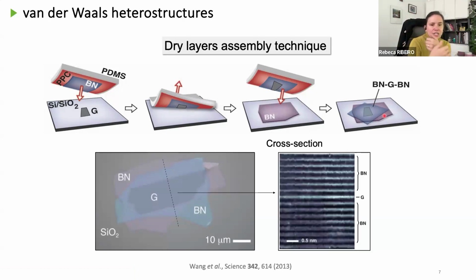And if we make a cross-section of this material, and we observe it by TEM, we can see that there is nothing between the layers. So there is nothing gluing the layers together. Here we are really talking about materials that are held to each other by van der Waals forces. That's, of course, why they are called van der Waals heterostructures. So, okay, we can put these materials on top of each other.